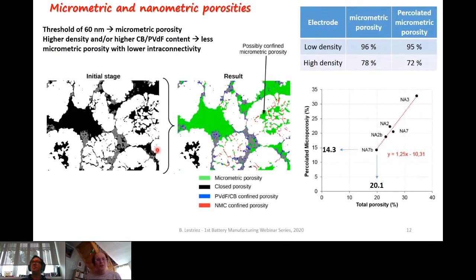So first, let's look at these 2D slices. This is after phase segmentation, and there we have differentiated the different porosities. First, you can observe in green what we have defined as micrometric porosity. This one was segmented by setting an arbitrary threshold at 60 nanometer. This is a visually arbitrarily set threshold.